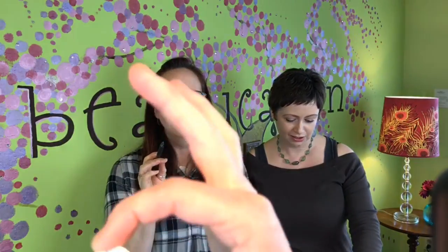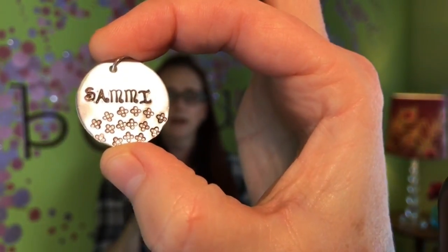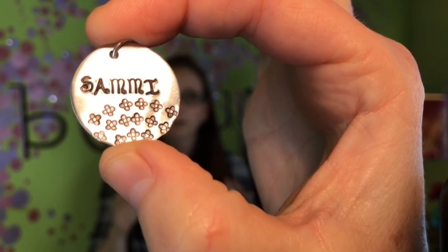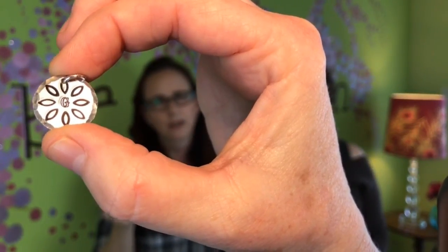One thing with the four dots that if you've done a lot of stamping, you guys have run into: if the stamp has a lot of surface to it, it's sometimes harder to impress, because remember you're moving the material and not removing it. So if there's a lot of solid space to it, like a solid heart or something, you may notice it's harder to impress. So you might need to anneal your metal, you might need a heavier hammer. Also, when you polish, sometimes it pulls the black out really easily, and that's just because you didn't get a deep impression. I hope that makes sense.